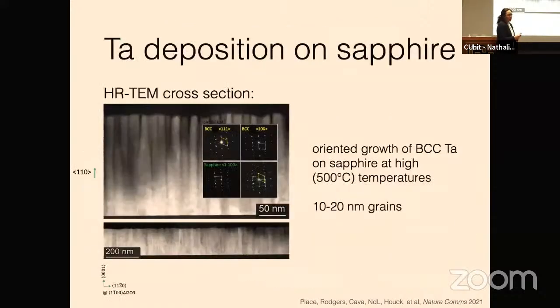To get rid of the niobium problem, we switched one down on the periodic table and used tantalum. Tantalum is a refractory material that is much more chemically resistant, so you can kind of throw it in a lot of different things to clean off the surface and fix your fabrication errors. And most importantly, it has a very nice stoichiometric oxide. There's one trick, which is that if you just naively deposit tantalum, you get the wrong phase. You get the beta phase, which is a tetragonal phase, whereas the bulk phase, which has a much higher TC, is a BCC alpha phase.